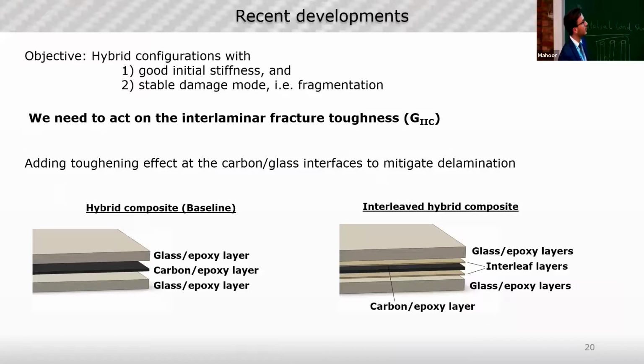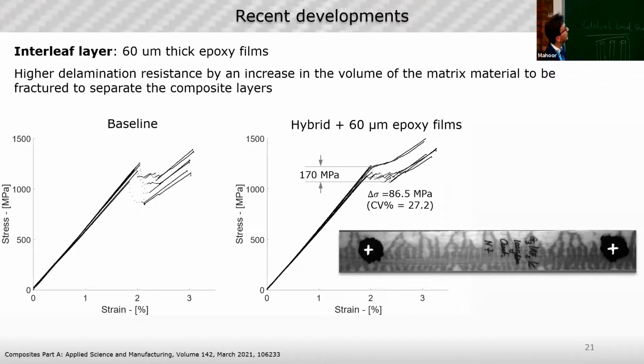The approaches we recently implemented at BME were to act on the interface using a standard thickness carbon layer. This way we may have a good stiffness of the material at the beginning, but we want to introduce some dissipation mechanisms, let's say energy absorption mechanisms, that try to suppress the delamination and let the carbon fragment. The approaches we tried were, first, I want to show you this, it was made just introducing layers of epoxy films. In this case, we can say in other words, this approach is affecting the volume fraction of the material between the interface of the carbon and the glass layer.